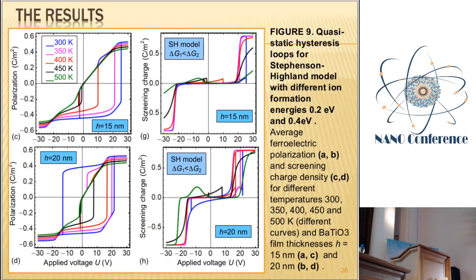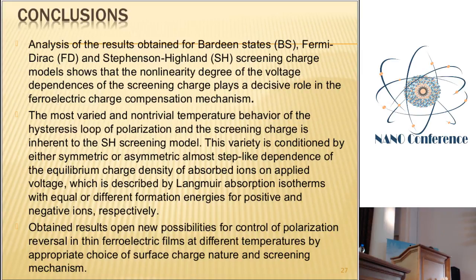So if the experimentalists know how to control the ion formation energies, it allows us to control the loop shape just by changing the ionic environment. And this is one of the main conclusions of this work. So, if you would like to control the ferroelectric polarization, you should choose two things. First of all, you should vary the thickness of the gap between the film and your imperfect electrode. Secondly, you should choose the screening charge which is asymmetric with respect to voltage, for example, ionic screening, and its dependence on the applied voltage should be nonlinear.